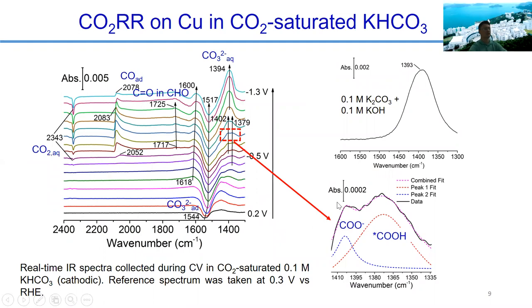So this is an FTIR spectrum during the carbon dioxide reduction on the copper thin film on gold. You apply the voltage from positive to negative. You can see there's a negative band, which is the carbon dioxide in the liquid phase. In the solution, this is negative, so that means a depletion of carbon dioxide. And we also have this very big negative band, which is carbonate ions in the solution. And this 1394 band is also carbonate, and this one is adsorbed on the surface.